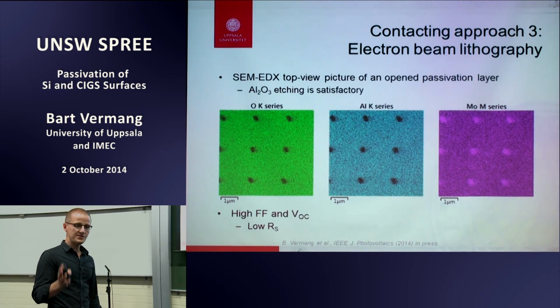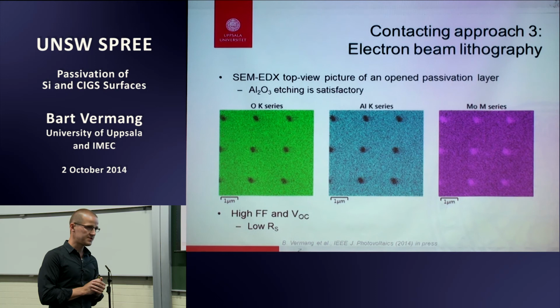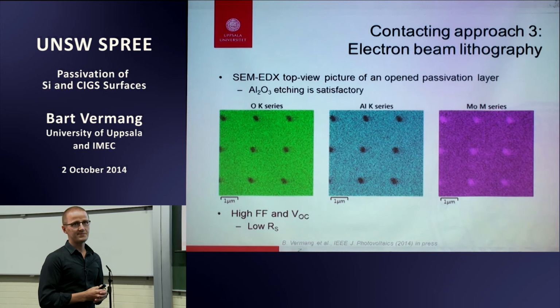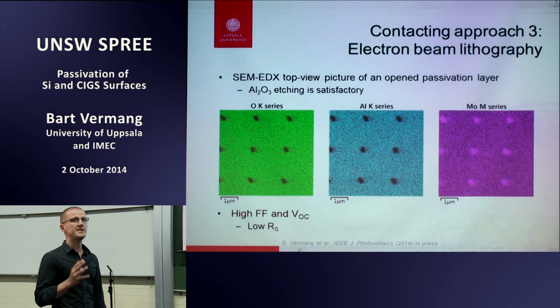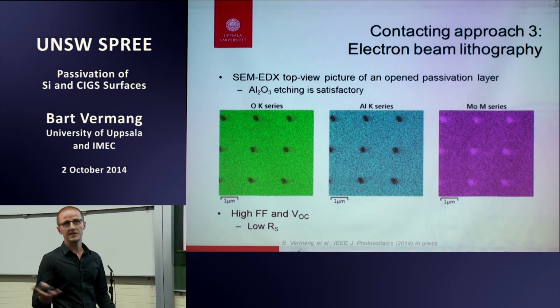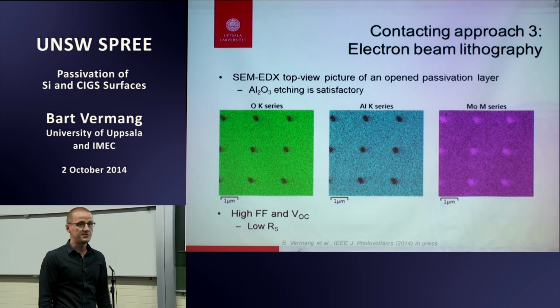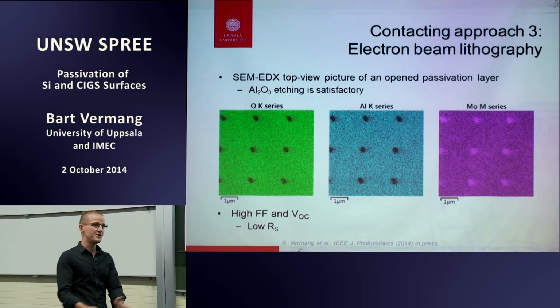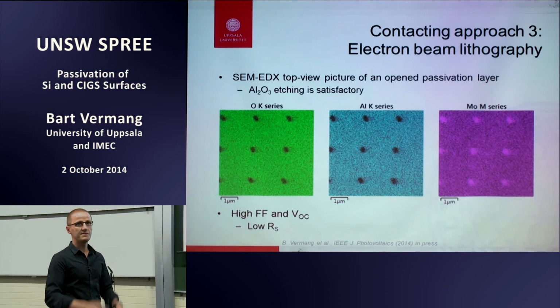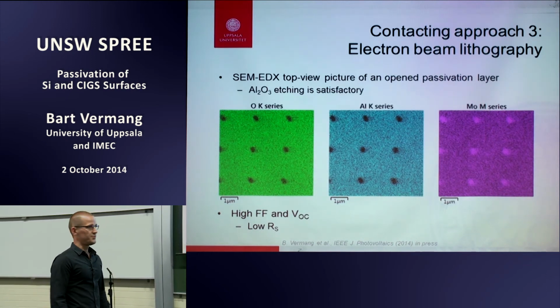We didn't try it yet, for certain reasons. But there is a paper out in Applied Physics Letters where they used ALD titanium oxide as a very, very thin tunneling layer on CZS. I would say it's not conclusive yet, because they use the same devices for the DLTS measurements and for the device measurements. You see an increase in VOC, and for the same cell, you also see an improvement of the interface defects, the DIT. But it's the same cell, so it's normal that you should see this. They put titanium oxide between the cadmium sulfide and the CIGS, very, very thin, just a few cycles, so it's kind of tunneling.